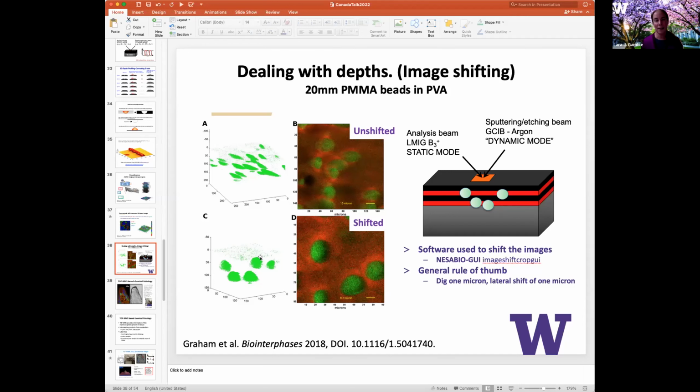There are a lot of other ways that people have tried to do it, like putting a sugar coating on, but not enough so you can just barely see it, is one way. If those aren't your options, really you're stuck with doing a very light glutaraldehyde fixation of your protein. I say really light because if you get too much of that cross-linking, it's going to affect your TOF-SIMS peaks. The amino acid peaks you would expect from your protein will change as you do too much cross-linking, because you're getting too many different types of bonds in there. Right, that makes sense.